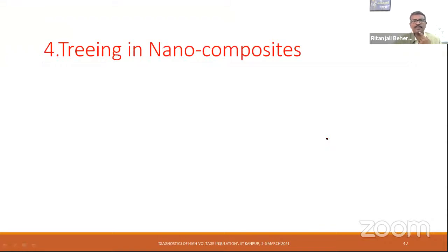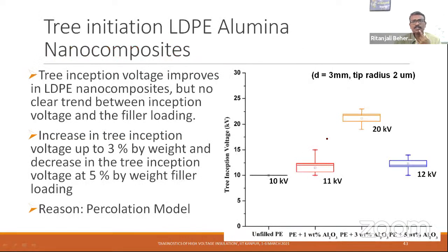Now the last part, treeing in nanocomposites. The tree initiation at the nanocomposites, LDPE alumina, can be observed here. For the first one, this is unfilled polyethylene, LDPE. The tree initiates at 10 kV. Whereas the tree initiates when the alumina as a filler is mixed with 1 weight percentage concentration, the tree starts at 11 kV. So the inception voltage is increased slightly. When it is 3 weight percentage, then the inception voltage becomes 20 kV. Appreciably increased tree inception voltage.